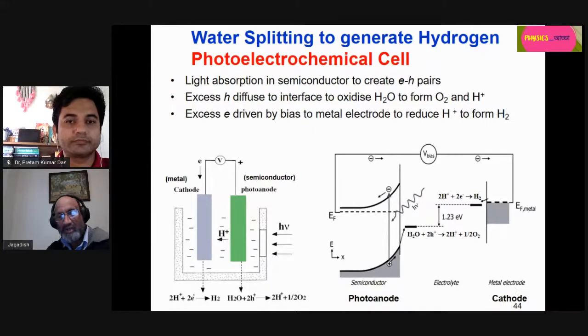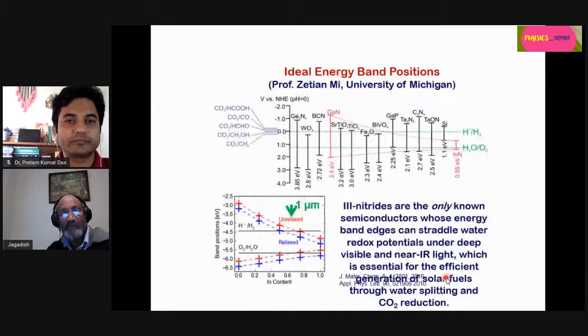And again, some of my colleagues are involved in this particular work. So here is a case where people have looked at what type of materials are the best. People typically use titanium dioxide, which has a large band gap. It can only absorb the UV light; visible light cannot be absorbed. Gallium nitride, same thing. It has a large band gap, which straddles the redox potentials of water, but it's not absorbing much light. Whereas indium nitride, which has a much smaller band gap, will be able to absorb most of the light, but it's not straddling the redox potentials of water.